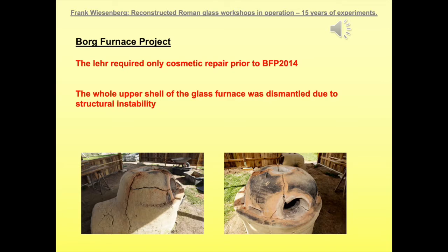Prior to the next big furnace project at Borg in 2014, some pretty crucial repair was required on the large furnace due to a little problem during the construction. The whole upper shell, the dome of the glass furnace, was unstable due to severe cracking. So it was dismantled and rebuilt in 2014.